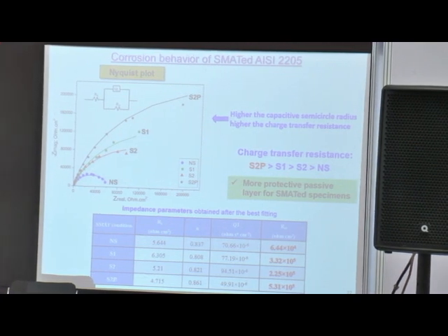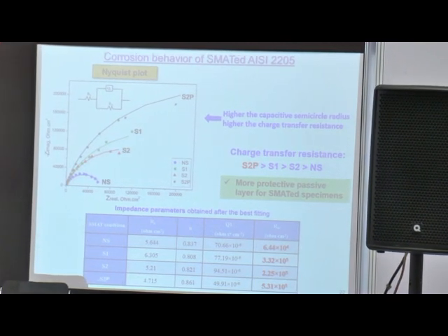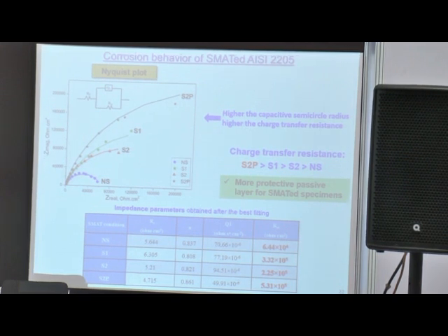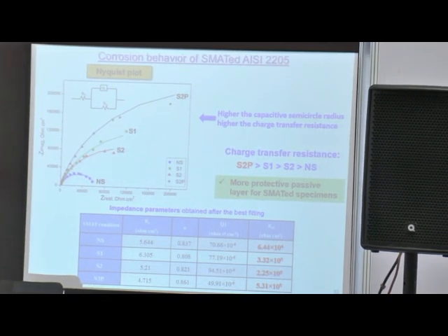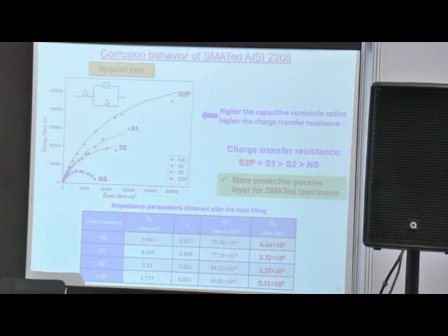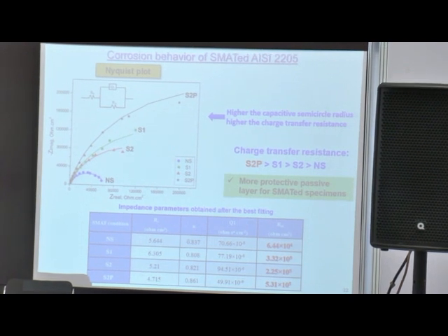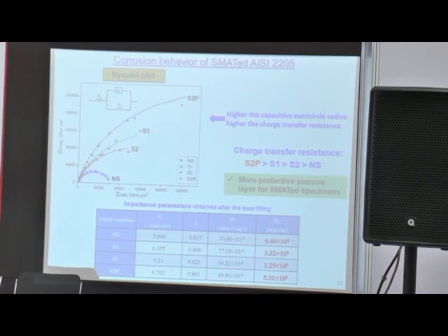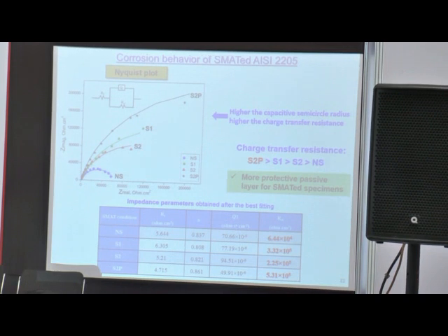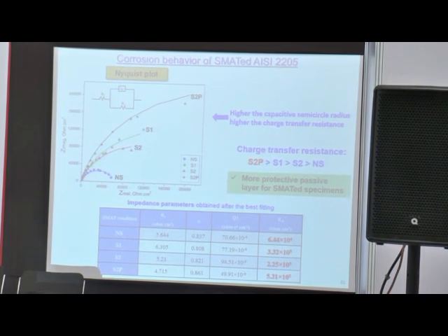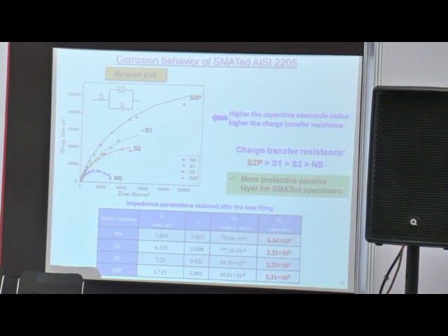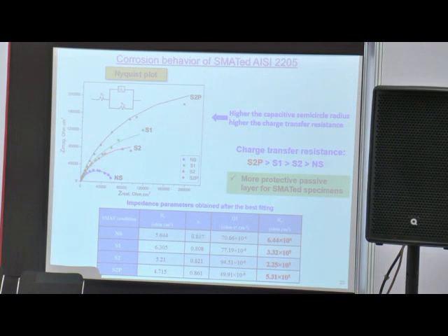There is another proof for that. As per the Nyquist plot, the larger the radius of the plot, the better the corrosion property. It shows the S2P sample, where S2 indicates the SMATing condition and NS indicates the non-SMATing condition. So the non-SMATed specimen has the lowest corrosion resistance. However, the S2P has a better or superior corrosion behavior. That means the passive film is quite stable there.